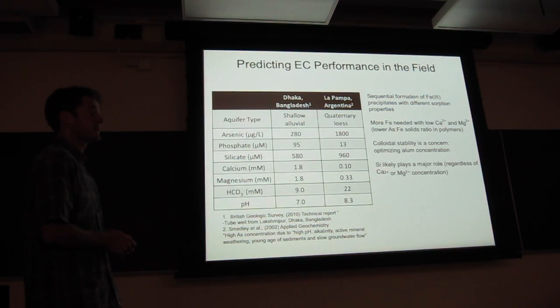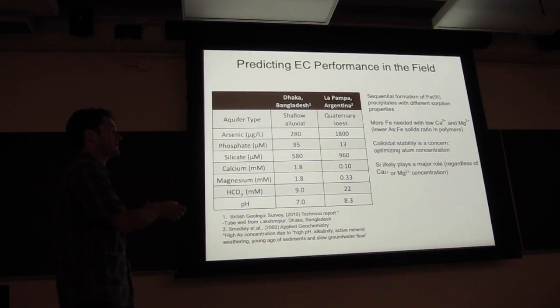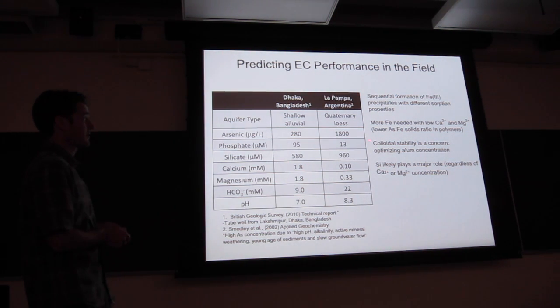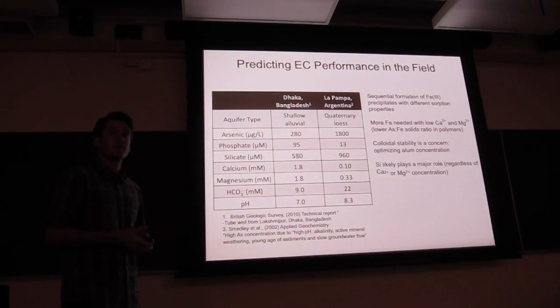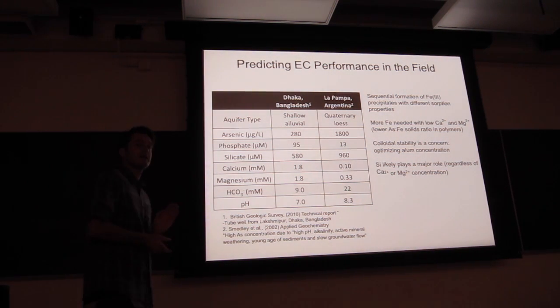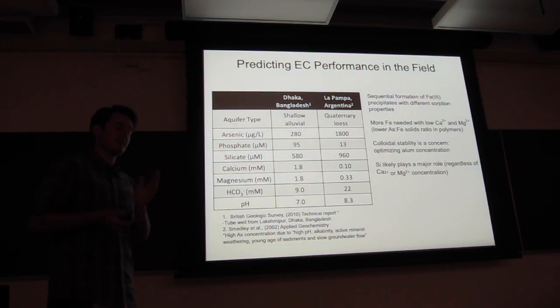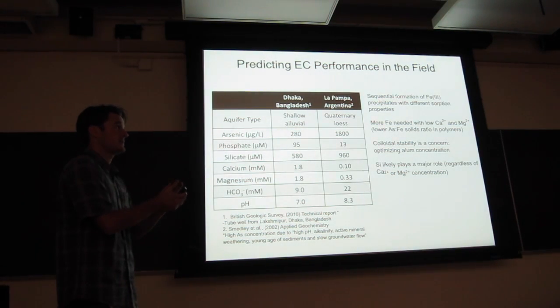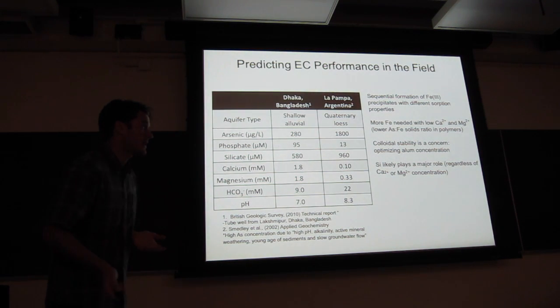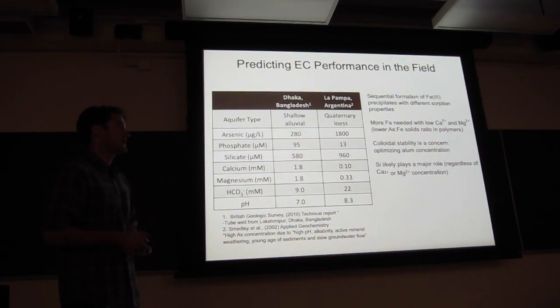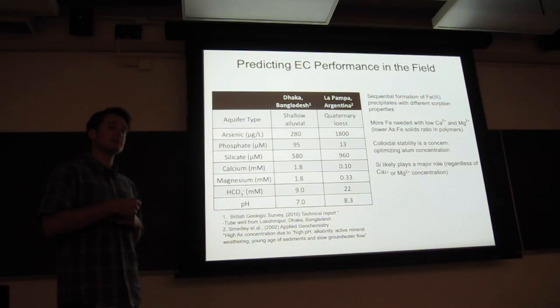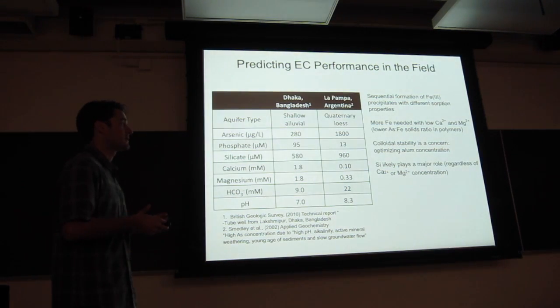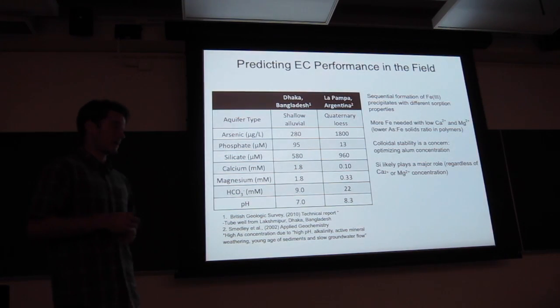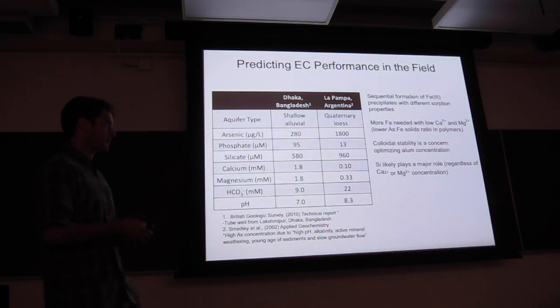I didn't really talk about silica at all. This presentation just focused on calcium, arsenic, and phosphate, but this is part of a larger project looking at silica as well. You can see that silica is at a pretty high concentration in both aquifers, and that's pretty common in groundwater. What silica does is, during the sequential formation of iron oxides, you get these polymeric precipitates at the beginning, and then instead of forming lepidocrocite, you're going to form another poorly ordered material. That's because silica binds in the same areas as arsenic and phosphate, but arsenic and phosphate have a stronger affinity for binding. So silica is going to really control the average structure.